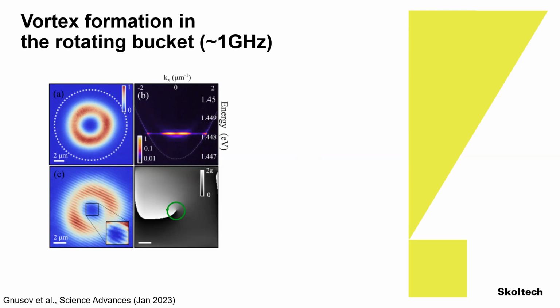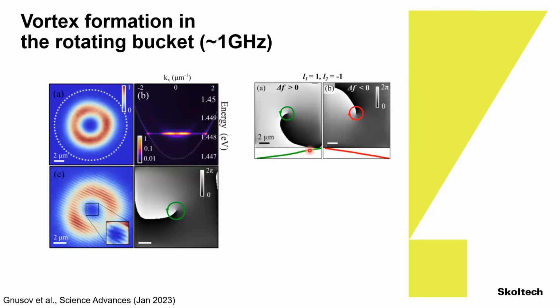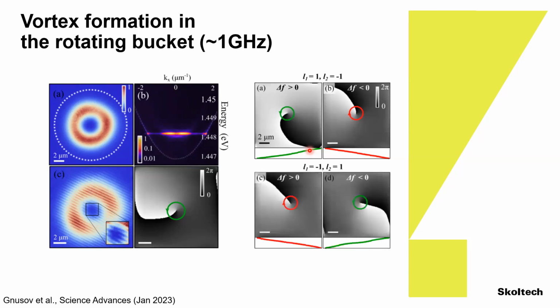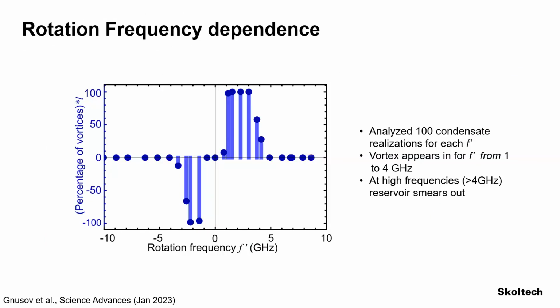And I can control the winding by controlling the rotation, either by changing the sign of the Laguerre-Gaussians or by changing the frequency of the Laguerre-Gaussians. And therefore, now I can play also with the frequency. If I rotate very slowly, 0 frequency, nothing happens. There is no vortex. Polaritons just escape within their lifetime from the gaps. If I rotate too fast for the dynamics of polaritons and that of the external reservoir, nothing happens. Once I go to between 1 and 4 gigahertz, I see that I get vortices with 100%